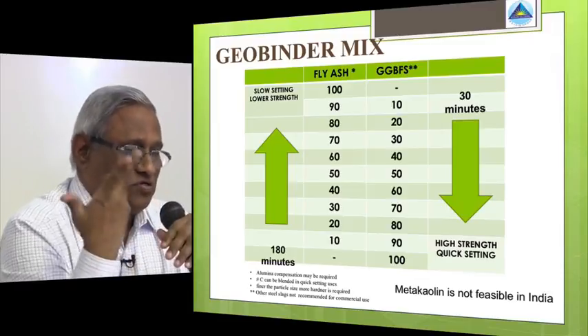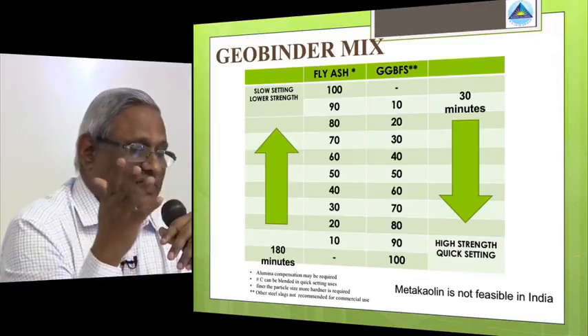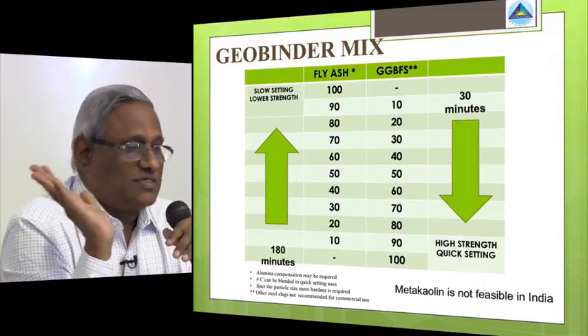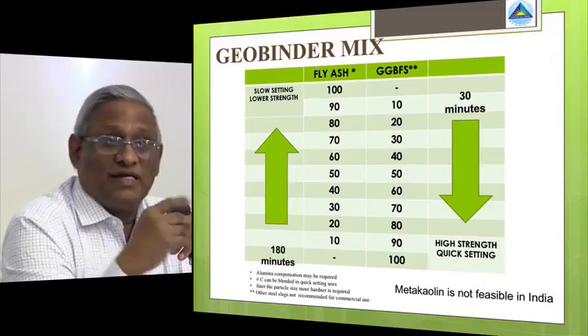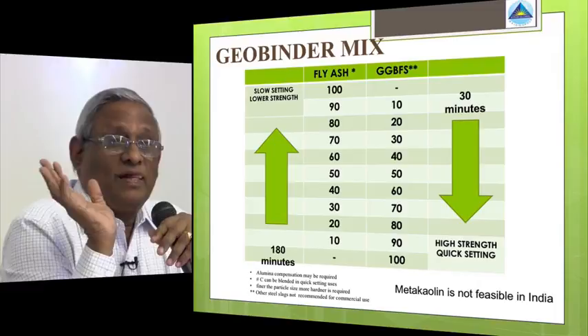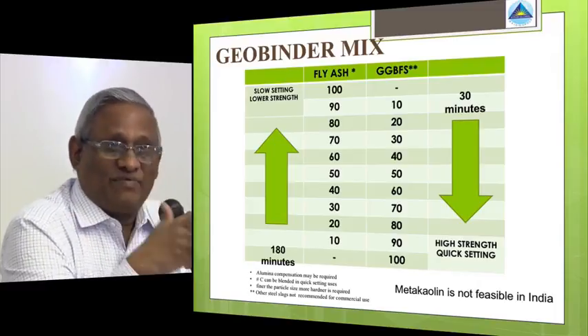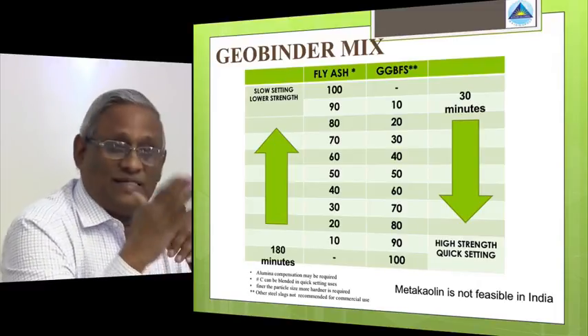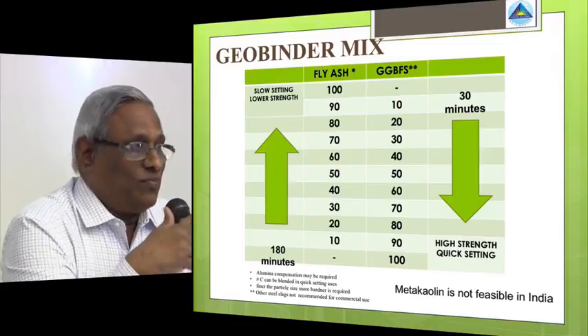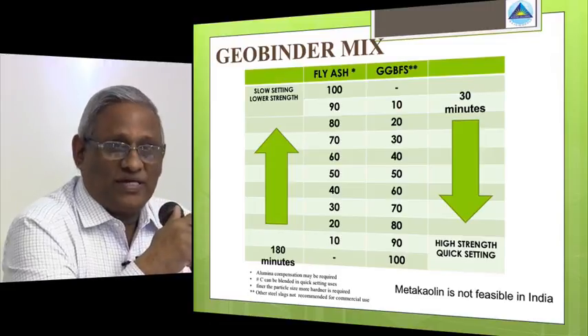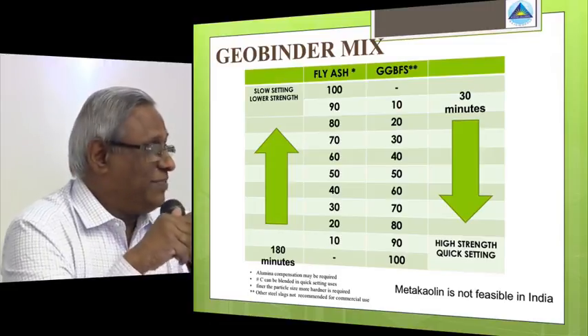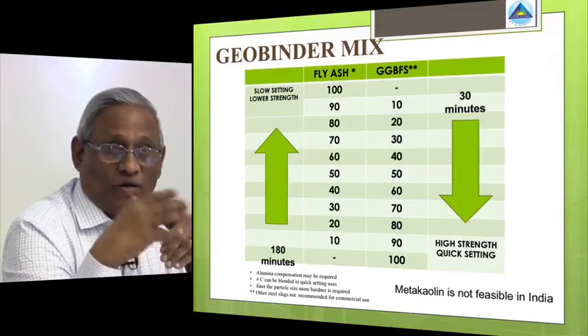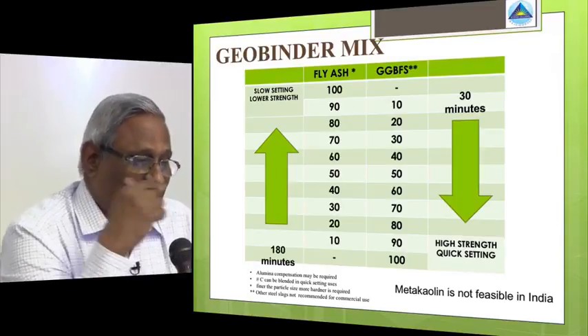Another very important slide is the ratios of fly ash and GGBS. It could be any of these ratios. It could be 50-50, 60-40, 70-30, 100% GGBS, 100% fly ash. Anything is possible. But the thing is, we have to use the right type of activator, and then what strength that you need. You add more fly ash, sometimes you get a lower strength, and you add more GGBS, you get a higher strength, and you get a quicker setting.